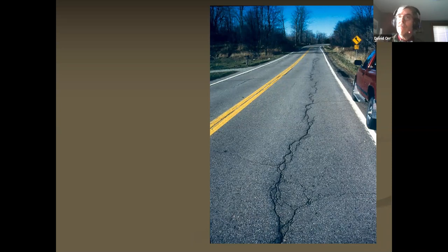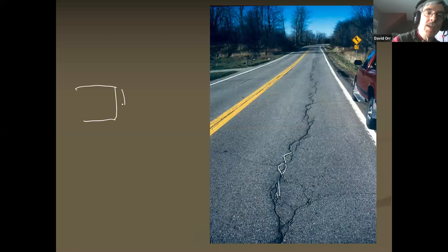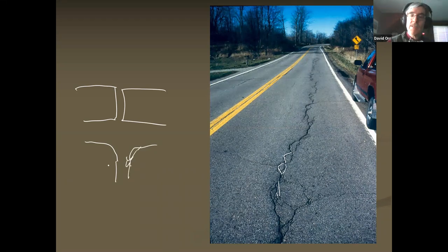Would take a lot to fill it in. Yep. Secondary cracks. Look at all the parallel cracks that you've got to deal with. Okay. Lots of parallel cracks, and it's too wide. If you put all those cracks together, that's probably going to be more than an inch. Okay. And then the other thing is, imagine if you were way down looking at it from below these cracks, if you did a cross section. Remember, we want a nice square edge. But what we really probably have here, you can actually see it, we've got this deterioration over here. If you see that much breakdown of the top, you're gonna have a really hard time.